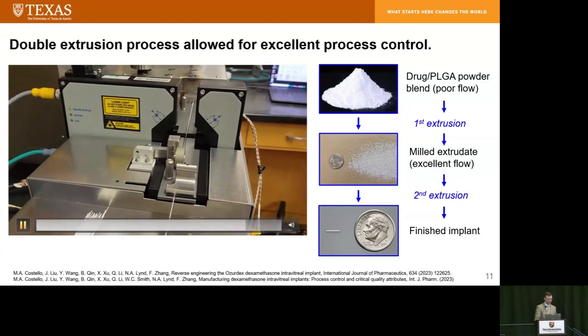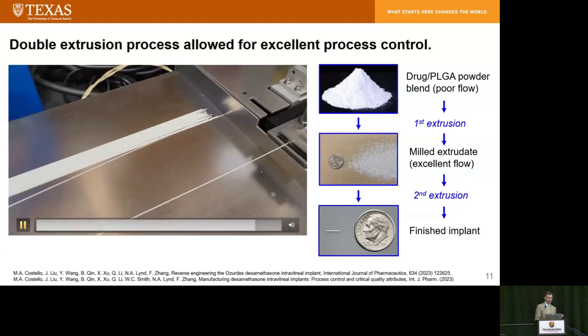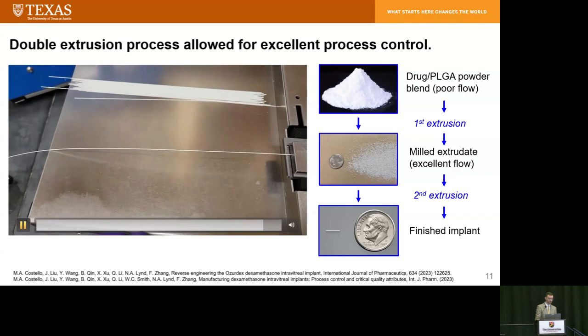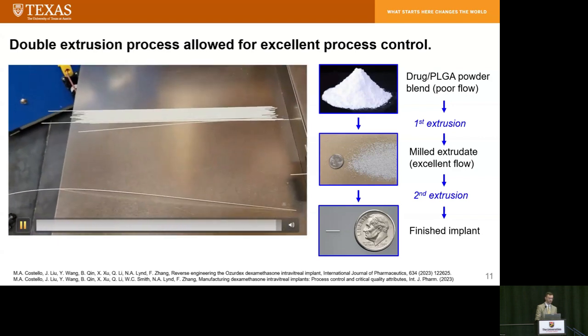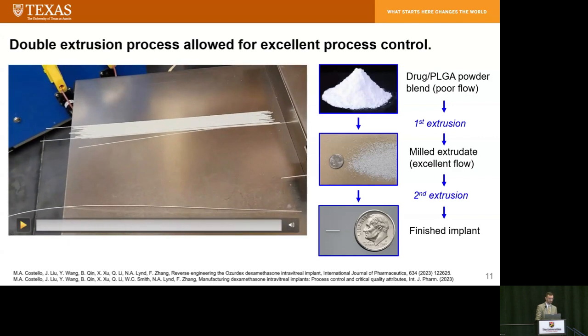So one thing I haven't explained yet is that there's actually 2 extrusions total in this process. So we just saw a video of one of those extrusions. And 2 extrusions are required for the following reason. Starting with the drug and PLGA powder blend, it's a very light and fluffy powder, which doesn't flow very well, meaning that the feeding process is not terribly consistent.